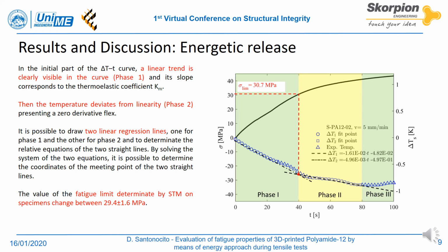For the three-dimensional printed static tensile test, an average value of 29.4 ± 1.6 megapascal has been found for the limit stress. Useful information can also be retrieved observing the temperature trend. In particular, it is possible to define a yielding stress in correspondence of the temperature zero-derivative flex region, in the transition point between phase 2 and phase 3. This stress can be thought of as the macroscopic stress at which the majority of the material crystals are under plastic condition.